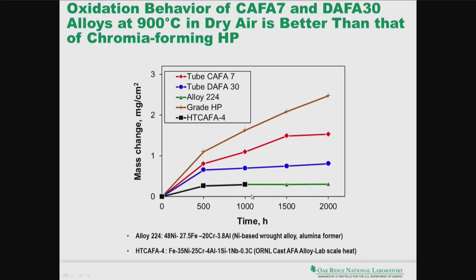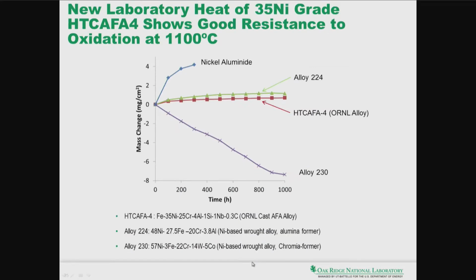What we also show here is a lab scale version of one of our alloys within the patent that starts to almost track the high nickel alloy. And this we call the HTCAFA-4, and this is the alloy that really holds a lot of promise for the higher temperature applications. And I'll show you at 1100 C, this is even better exemplified.